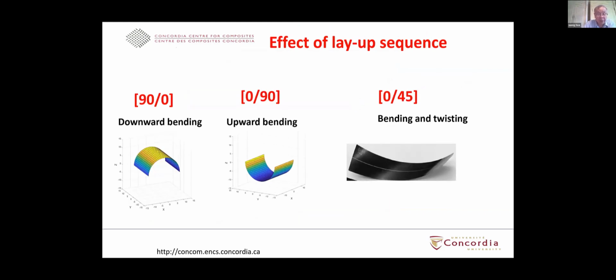So for example, here, the main mechanism we use is a layup sequence to create a change of the shape from flat to curve. If you use something like a 90-0 layup sequence, then you end up with a downward bending structure. If you change the order of the layup sequence from 90-0 to 0-90, then you end up with a structure that is concave upward. And if you use something like a 0-45 layup sequence, in addition to the bending, you also have twisting as well. So basically, that is the idea behind the 4D printing of composite method.